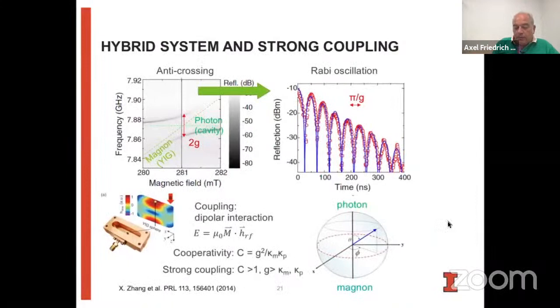And when you have this coupling, what happens is that the excitation periodically goes back and forth between being a photon and a magnon. And so if you just measure the intensity of the photon mode in this coupled state, you actually see this oscillatory intensity, which is known as Rabi oscillations. And the periodicity is directly given by this coupling strength. And so you're in the strong coupling regime if this coupling strength is larger than the coherence time of either the magnons or the photons in your system. And so you can define an important parameter, which is called the cooperativity, which is the coupling strength squared divided by these two coherence times. So if you want to have a coherent interaction between these two excitations, you want to have this cooperativity larger than one. And that's what we call strong coupling.